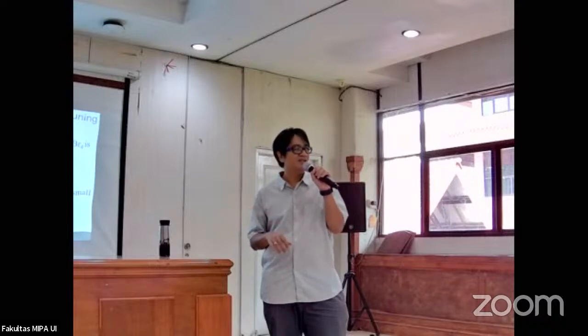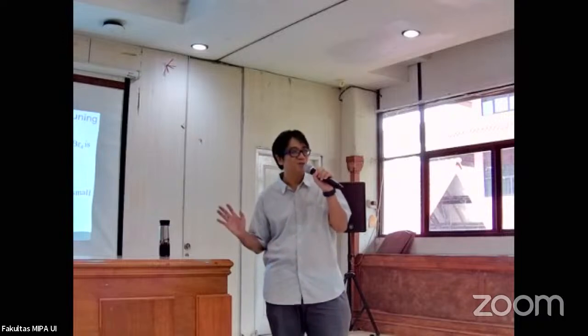But cobalt, surprisingly, defeated us almost emotionally, because Afif said he tried everything under the same literature guide. But I said, no, no, no. Now it's time for us to play the devil. So we go in a completely different route. I said, okay, increase the halide, because normally that's one thing we do with Miyasaka when he grew the MAPbBr3 back then. Apparently, this helped us to nucleate the main thing we are looking for, the single crystal. But for your case, at least two things you need to take more carefully: the mixing ratio and the purity of your precursor. I hope that can give you a bit of enlightenment.